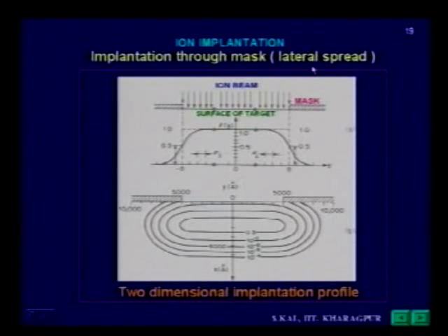Although it has been told earlier that the implantation technique will have no lateral spread, that is only in case of diffusion. Even then, because of the mask pattern, it has been observed that a small lateral spread is also there in case of implantation. That means the profile is not exactly vertical, but some spread in the lateral direction has been observed. And that is for a finite thickness of the mask, because the mask edge is not exactly vertical, some tapered line is there.